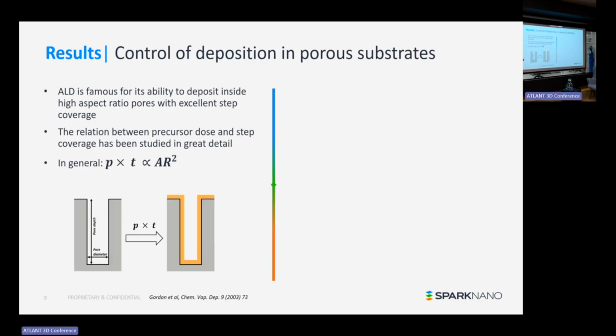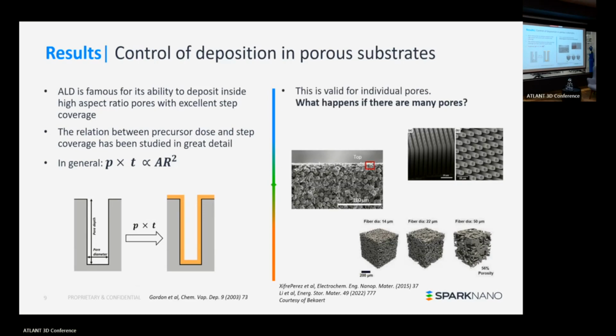So, of course, ALD, as said, is very famous for its ability to coat high aspect ratio structures, and the relation between things like precursor dose, the precursor concentration and exposure time, and the aspect ratio of a pore has been studied in great detail by many people worldwide. Roy Gordon was one of the first publishing on this topic, and many ALD experts will recognize relations like this: in order to conformally coat a pore, you need to apply a precursor with a certain concentration and exposure time, which scales with the square of the aspect ratio, which is the ratio between the depth and the diameter of the pore. So this is true for an individual pore.